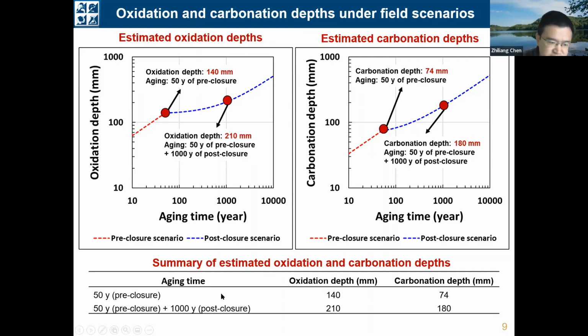The major reason for that is that under this pre-closure scenario, the aging relative humidity is only 54%, which is lower than the aging relative humidity under the post-closure scenario. So lower relative humidity will facilitate the moisture transport out of the concrete and also facilitate the ingress of oxygen and CO2 into the concrete. So the aging rate under the pre-closure period is much faster compared to the post-closure scenario.